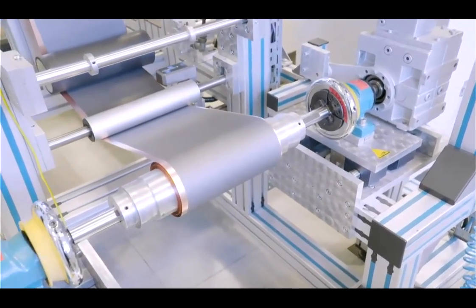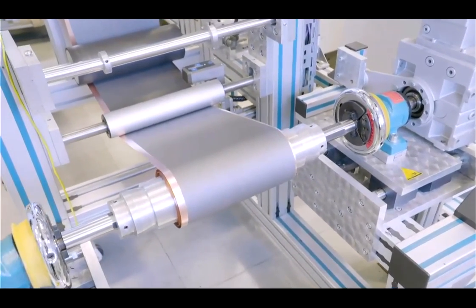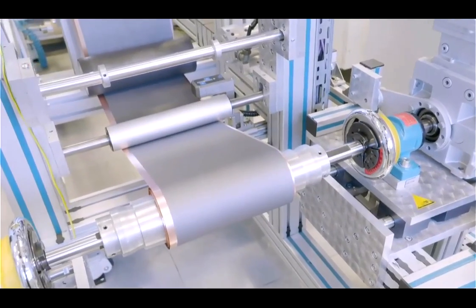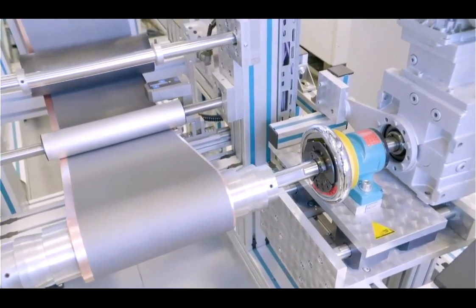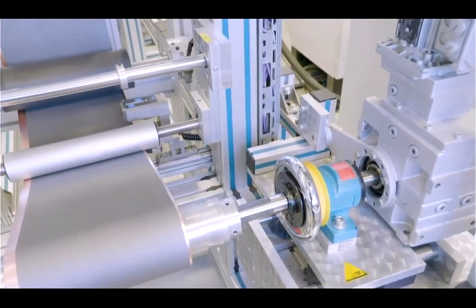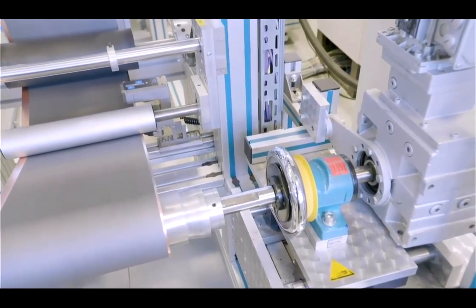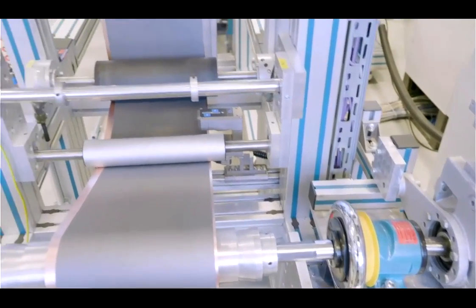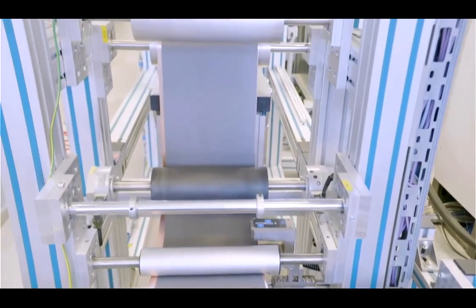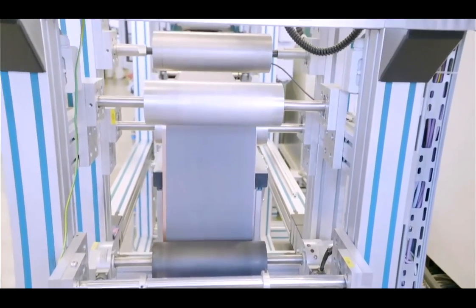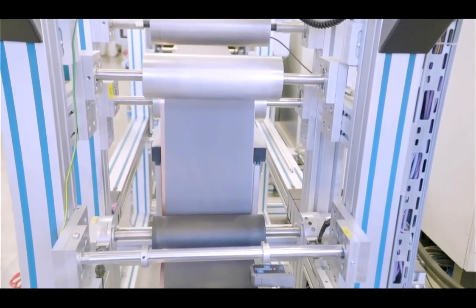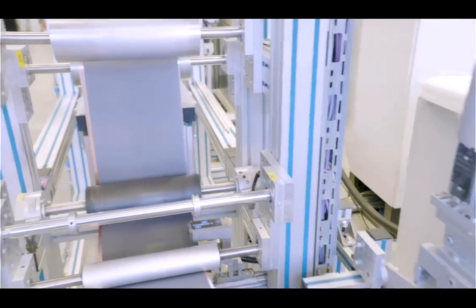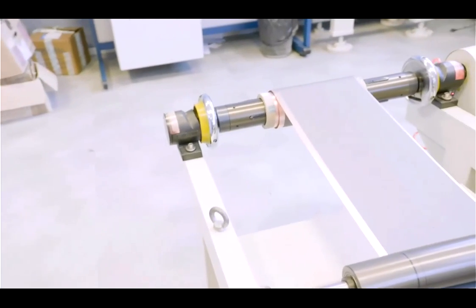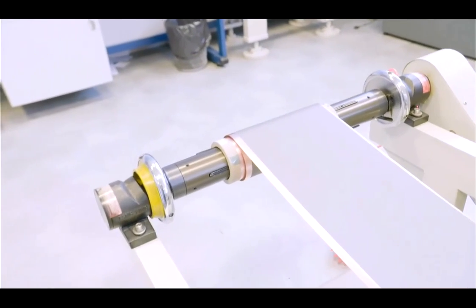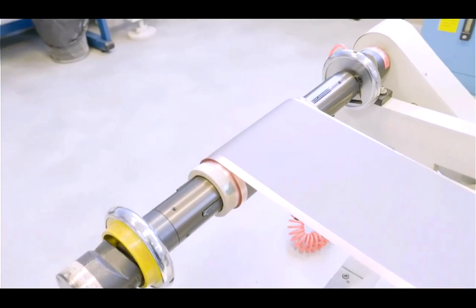Coating quality: it is very important to have thickness accuracy. We need homogeneity, not just in the coating direction, but also across the direction of the coating. As you have seen, we just coated one side of the electrode. To do the second side, we take the roll and put it back at the beginning of the machine, and we do the coating on the second side.